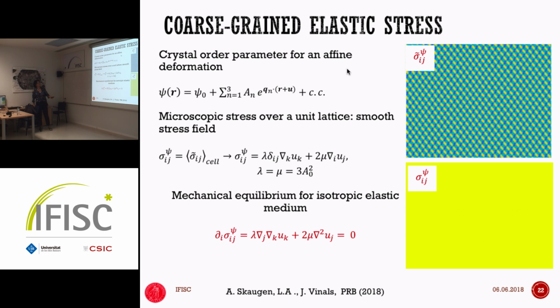In order to show this, for example, we can use the one-mode approximation where we distort the phase field density, this order parameter, by applying a smooth deformation field in the phase. Okay, and if we carry out this expansion into the definition of the stress field and average over the unit cell, we end up exactly with the linear elasticity rheology, a relationship between the stress and the strain. And in particular, all of these coefficients, the Lamé coefficients, are directly related to the equilibrium amplitude. So the elasticity coefficients depend on the quenching depth and the density that we're fixing. And at equilibrium, this directly translates to mechanical equilibrium: the gradient of the stress, which is the force, equals 0.